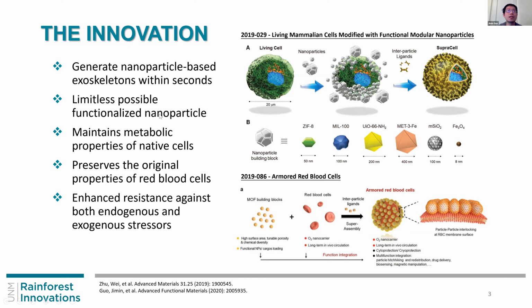Also, because we are using nanoparticles, we can use the metal organic framework particles, this three, and also this four. And also we can use the silica, mesoporous silica nanoparticle, and also the iron oxide, that magnetic nanoparticle. We can try different types, even polymer ones. We are still trying to optimize that one right now.